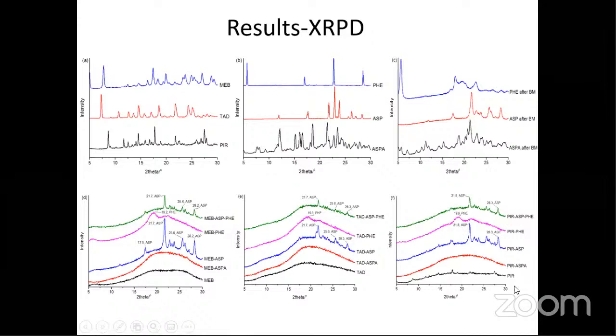And piroxicam cannot become amorphous alone, right? We can see the peaks here after milling. We can see from here, right? And piroxicam with aspartame, very nice, it is already amorphous. And aspartic acid and phenylalanine and the physical mixture of these two, all of them failed because we can see obvious peaks here.